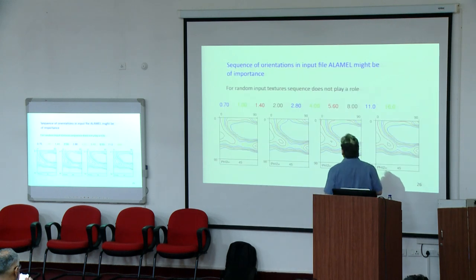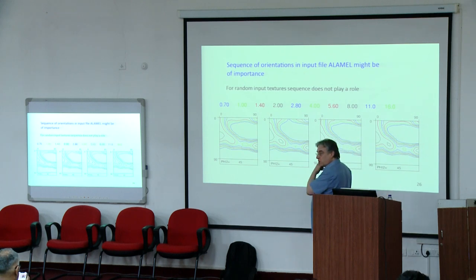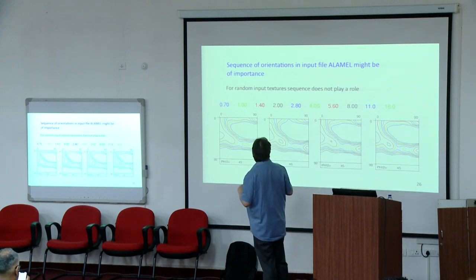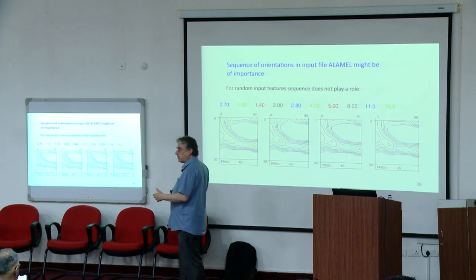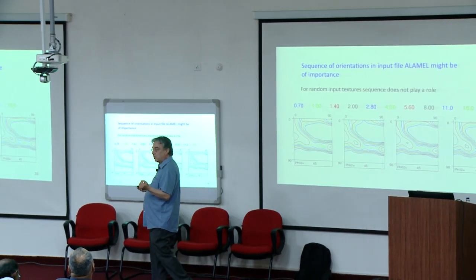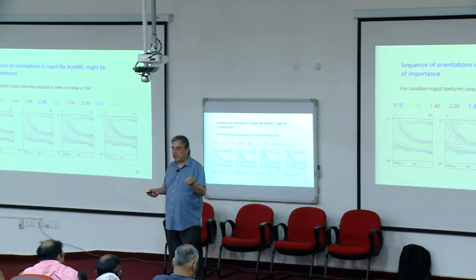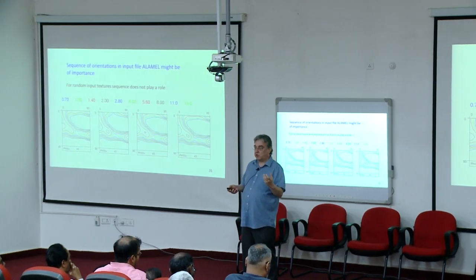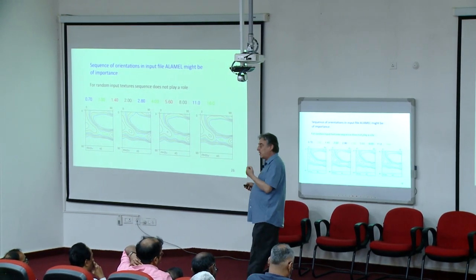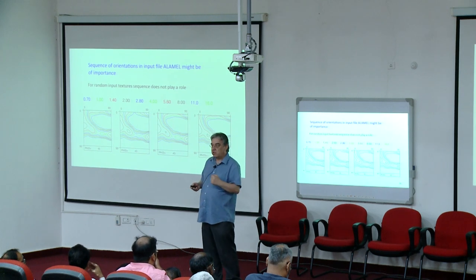But here you can see that the sequence of orientations in the input file may be of importance, but in fact, it does not play a role. And these calculations show it. These are 4 simulations with 4 different pairings. So this is what I call a topological assumption. Of course, this works only in specific conditions.